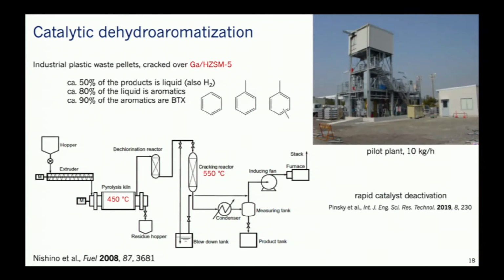So one way to do this is to simply heat your materials up with or without a catalyst. As I said, the catalyst can change the selectivity of the process. And if you do this in a process that involves a zeolite-based catalyst, you tend to get lots of aromatics. And there are these light molecular weight aromatics that we call BTX, benzene, toluene, and xylene. So in this particular process from Nishino in Japan, there's an initial pyrolysis step followed by catalytic cracking over the gallium-doped ZSM5 catalyst, which gives high yields of these BTX aromatics.